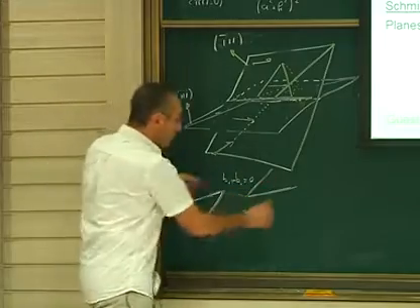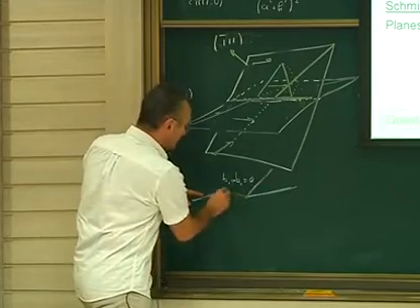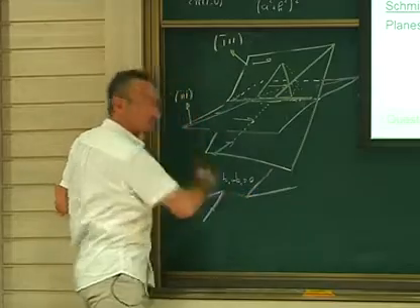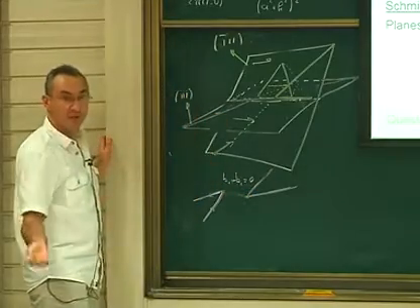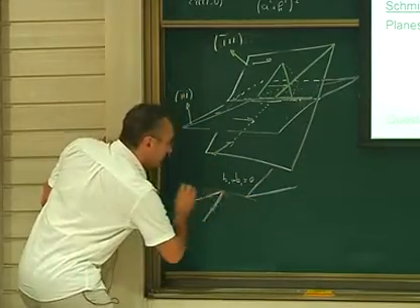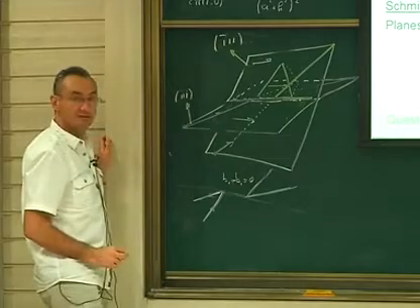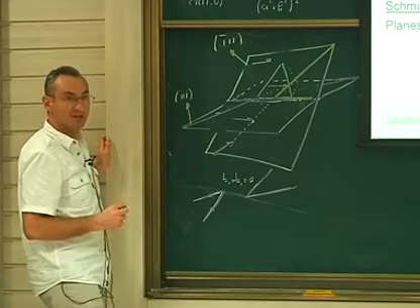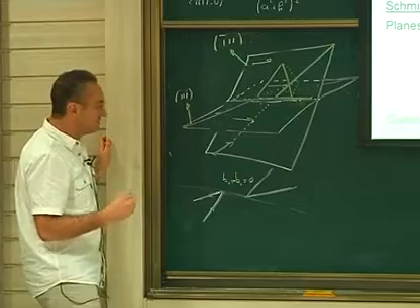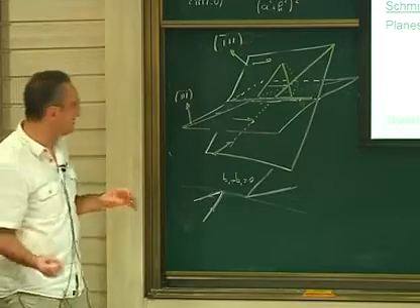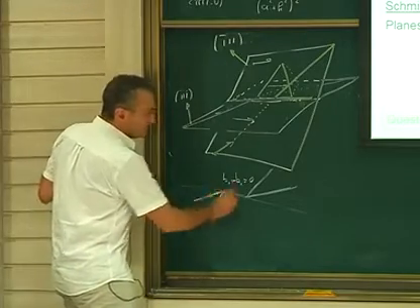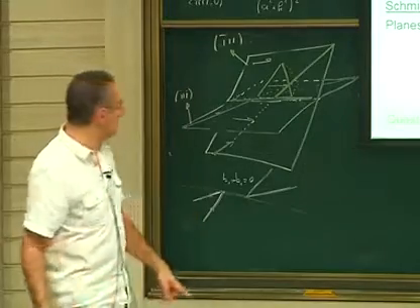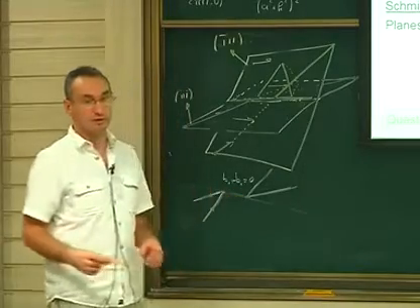So you have something which is strong because this point is mandatory to move along this line. So now this point is not free to glide in all the possible planes as before. It has to glide on the common point between the two lines. So this is strong. This is something which is very important in material. The collinear junction is very strong in the hardening mechanism, just because this pinning point is now no more free to move in the plane. It has to be always in the 1,1,0 direction, corresponding to the Burgers vector of the line.